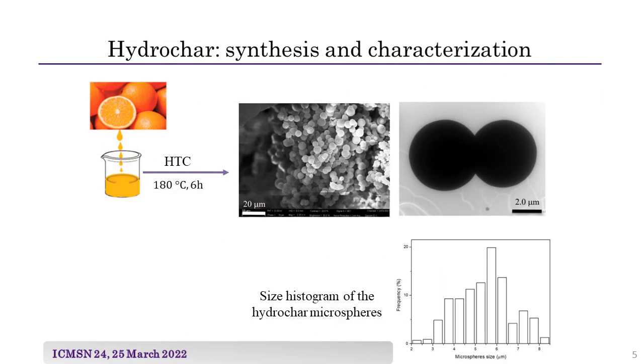In this work, I present to you a study in which pure orange juice was hydrothermally carbonized and the resulting hydrochar was filtered, washed, and activated by potassium hydroxide in nitrogen atmosphere at 800 Celsius degrees. The hydrochar obtained from orange juice was in the form of microspheres with a well-defined surface, as shown in the SEM and TEM images. Statistical analysis of the size of the spheres gave the histogram shown in the slide, from which we calculated an average value and a standard deviation of about 5 and 1 micron respectively.